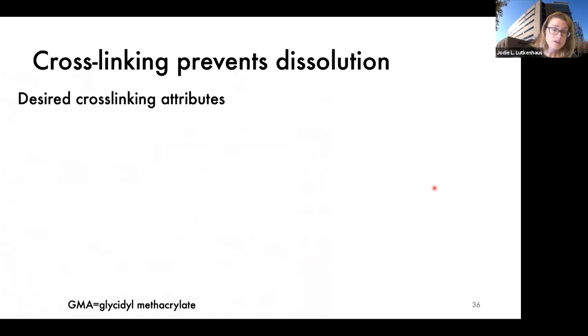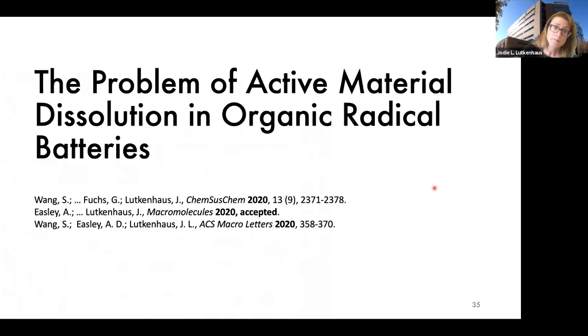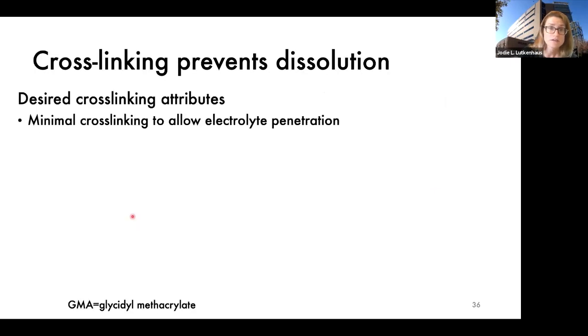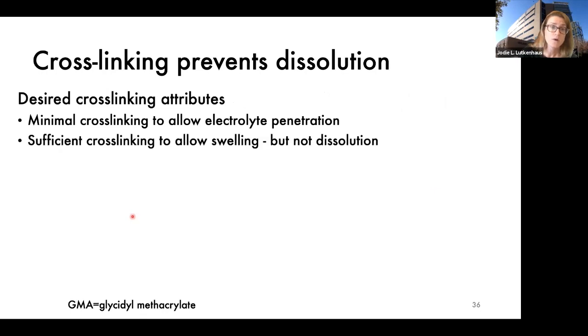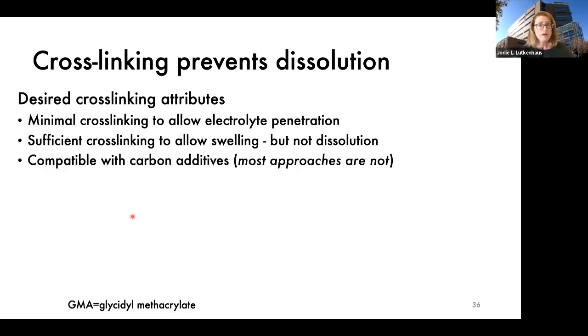So one way to address dissolution is through cross-linking and then solvent selection. I'm highlighting a few papers that we published that go over that. For cross-linking, we want to cross-link the polymer, but not too much, because we want the electrolyte to still get in there. So swelling is okay, but not dissolution.